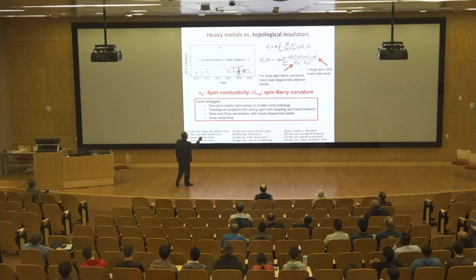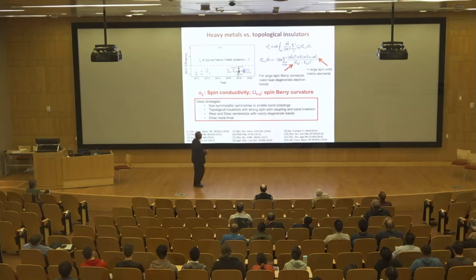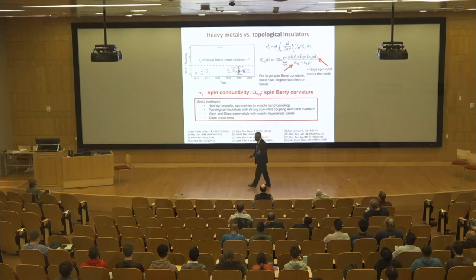Okay? And if you look at the physics behind this, the spin conductivity, sigma, has got a lot of different terms, but one of them is this omega, which is a spin-Berry curvature. Okay? That's given by 2 terms. One is the degeneracy of the electronic band structure, and that's the difference in these 2 energy scales. You don't want to be very different, okay, because that goes into the denominator. The numerator is basically the matrix elements for spin-orbit coupling. So if you have materials which have heavy elements, platinum, tungsten, tantalum, all of them have large matrix elements for the spin-orbit coupling. That's what people have used out here. And we were saying, guys, it would be much better if you used oxides. Of course, there are some materials like bismuth selenide which also work very well.